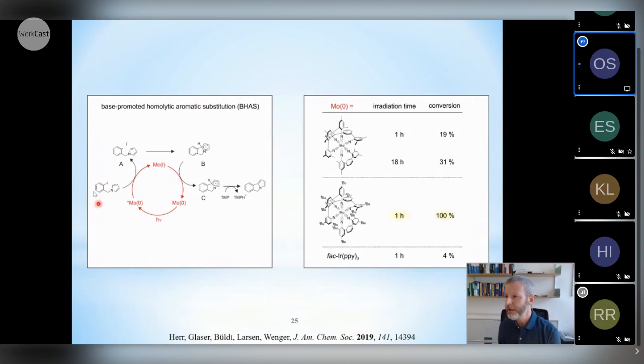This is a reductive dehalogenation reaction that is key here, the step leading to radical intermediate A and iodide anion here. This is the photochemical key step that cannot be catalyzed by typical iridium sensitizers because they are not reducing enough. The methyl substituted complex of Larsen can do it a bit, but it degrades over time, so you will never run that reaction to completion. However, the new Felix and Patrick catalyst here with the t-butyls at the periphery does catalyze that reaction rather beautifully.